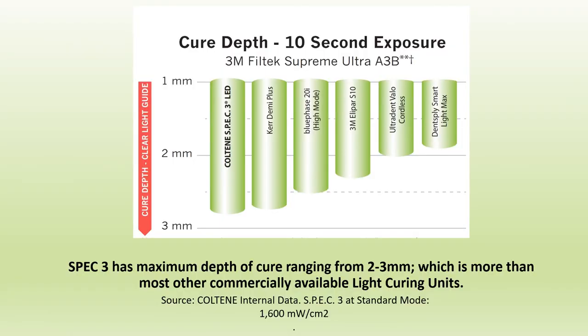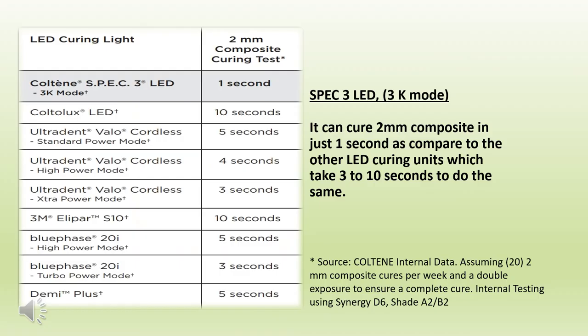SPEC 3 has maximum depth of cure ranging from 2 to 3 millimeters, which is more than most other commercially available light curing units. It can cure 2 millimeter composite in just 1 second as compared to the other LED curing units, which take 3 to 10 seconds to do the same.